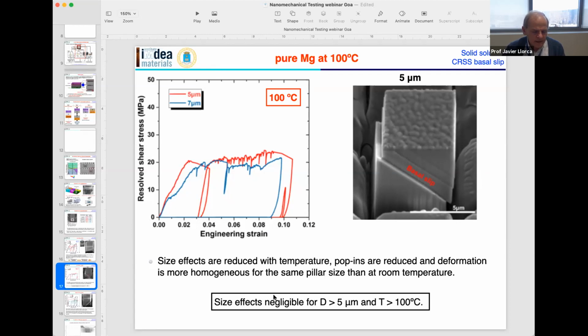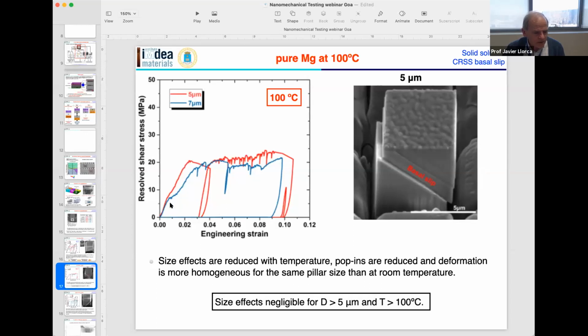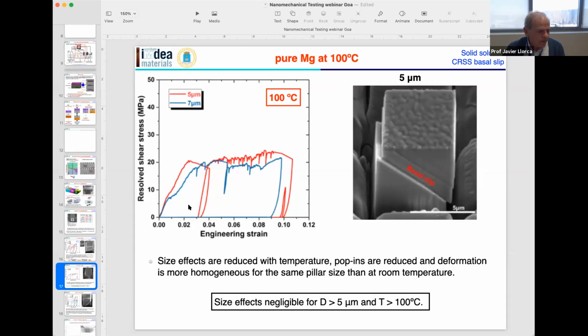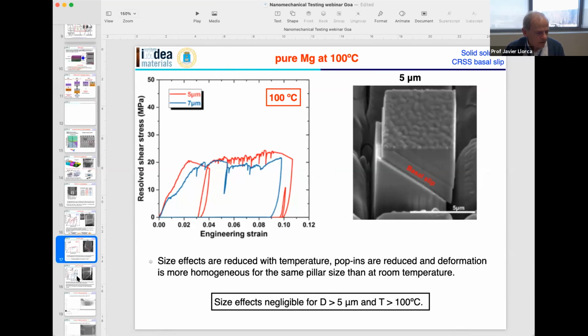And basically, in this particular material, size effects are negligible when the size of the pillar is over 5 microns and the temperature is 100 degrees Celsius. So with this technique, we can really measure the critical resolved shear stress using micropillar compression. This is just for pure magnesium. But what happens if we go to a magnesium-aluminum alloy?